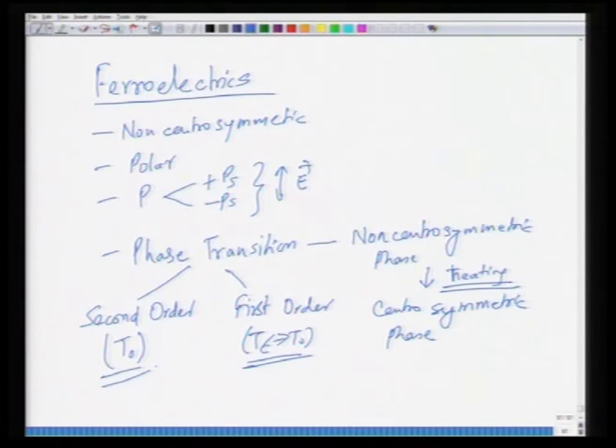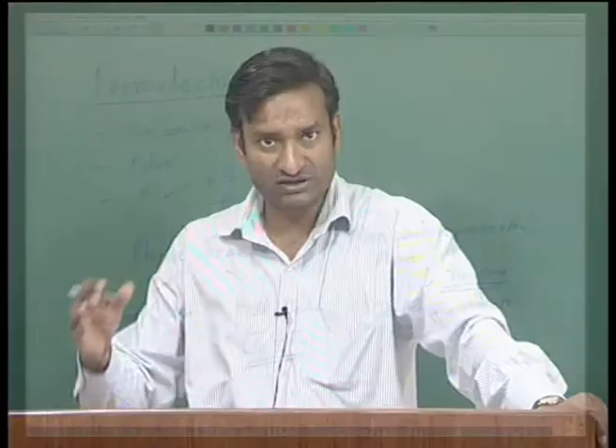The difference between these two transitions is that in the second order transition the polarization drops continuously up to the transition. In the first order, the polarization drops abruptly at the transition. So there is a discontinuity in the polarization, which is called the order parameter, for the first order transition, and it drops suddenly at the transition temperature. This is also shown in the susceptibility of the first order transition, which shows the discontinuity. Another difference is in the second order transition you have discontinuity in the specific heat near the transition, but there is no evolution of latent heat. In case of first order, you have discontinuity in the specific heat, but you also have evolution of latent heat. So it is like liquid to solid transition in some sense, the first order transition in ferroelectrics.